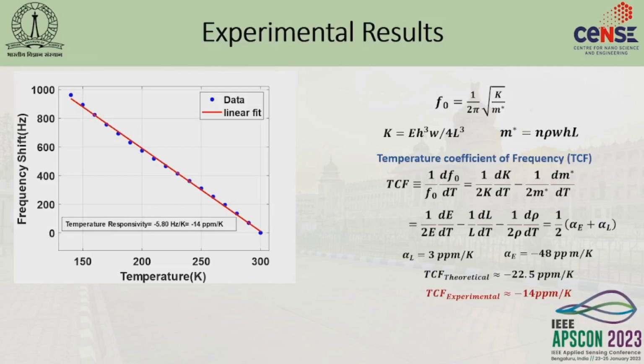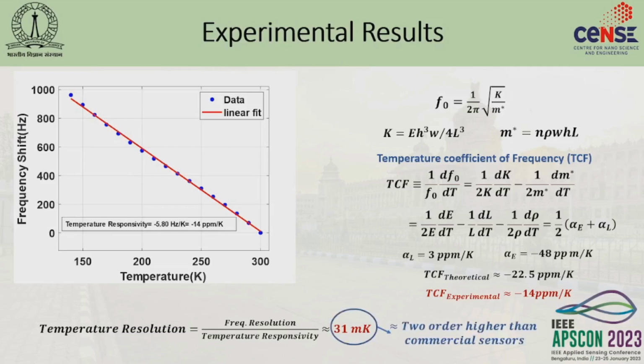This slight difference may be due to the thermal stress present in the cantilever, which is reducing the stiffness of the cantilever. So, this value I have used to calculate the temperature resolution. The frequency resolution we have already calculated in the previous slide, which was about 0.18 hertz experimentally, and the temperature responsivity is about minus 5.80 hertz per Kelvin. Based on this, this is the minimum temperature resolution that we can measure with this device, and this is about 2 orders better than the commercial sensors available in the market, like RTDs, thermocouples and thermistors.